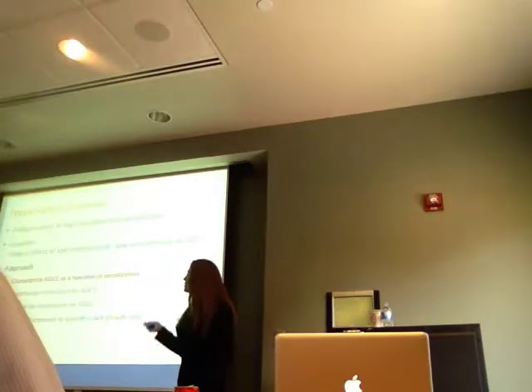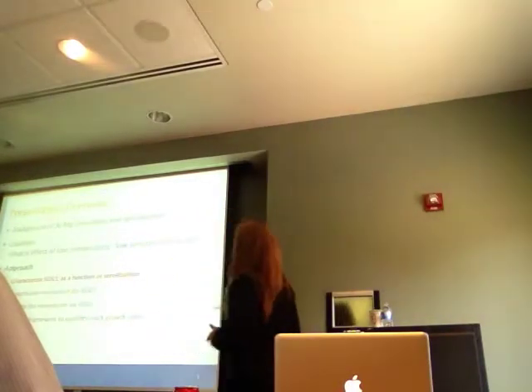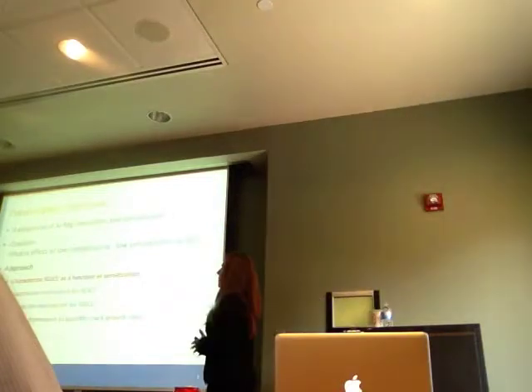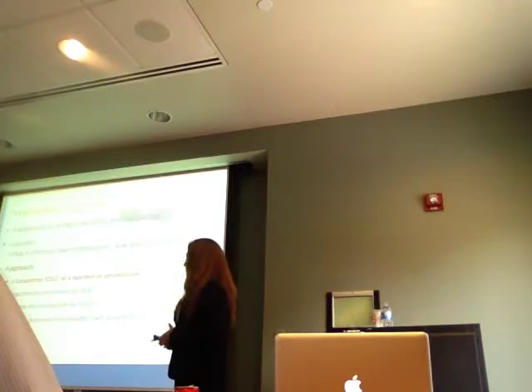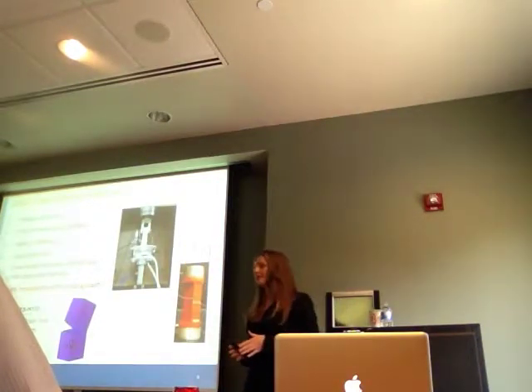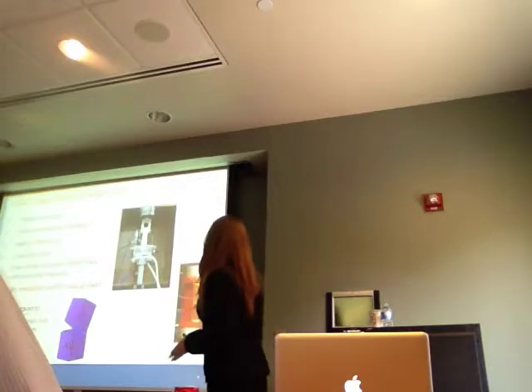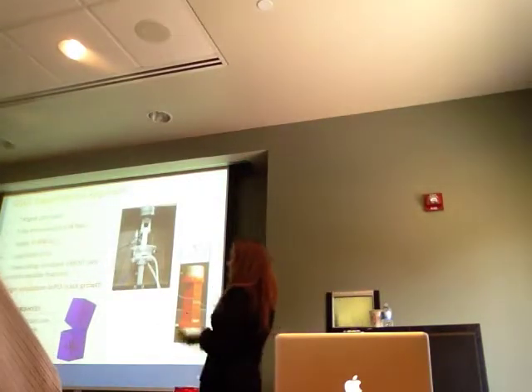Okay, so now that I've gone through our background on the question, I'm going to move on to our approach. And the first thing I want to do is characterize the intergranular stress corrosion cracking as a function of sensitization. To do this, I used a subcritical crack growth experiment. I used a single-edged notch tension specimen with the crack growing in the L direction, so along the grains, the worst case scenario for cracking.